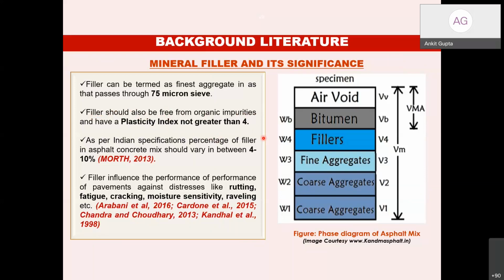Okay, but as per the Indian specifications, the filler in a whole asphalt concrete mix consists of something like 4 to 10% by weight. Okay, so that is the amount of the filler. So almost 7 to 8% of the mix is filler, and if you are directly using some waste kind of material, it can save a significant quantity of our economy also. Now, again, as I discussed, filler has an influence on the performance of pavements against distresses like rutting, fatigue, cracking, moisture sensitivity, raveling, etc. And this has been shown by various researchers.